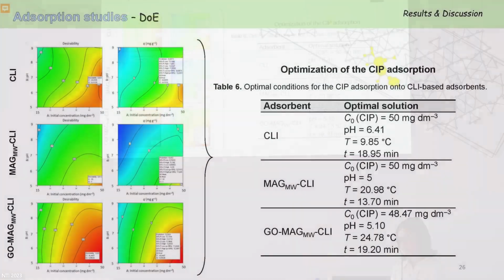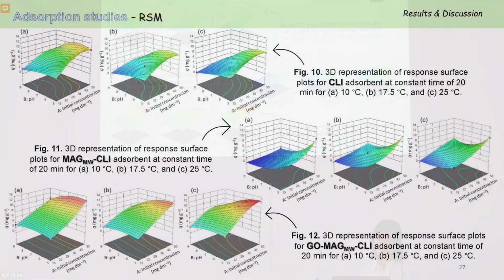Okay, further, the design of experiments enabled the determination of the variables that have the most significant impact on the ciprofloxacin adsorption. From those most significant parameters, contour diagrams were obtained, and they enable the determination of optimal conditions for the adsorption of ciprofloxacin on every synthesized adsorbent. Then three-dimensional surface plots were determined to see the interactive effects of initial concentration and pH for all three adsorbents at different temperatures and at a fixed contact time of 20 minutes.